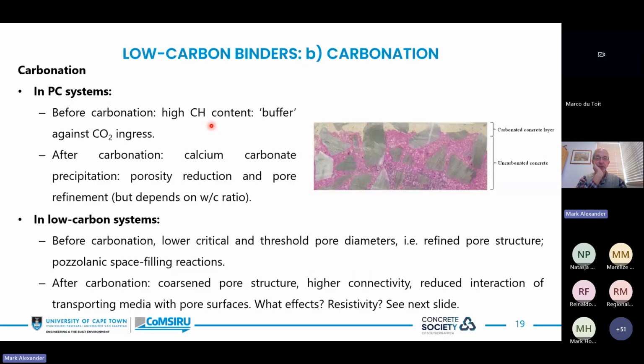Now, talking about carbonation, that's the other issue that frequently causes reinforcement corrosion. Here in PC systems, plain cement systems, before carbonation, we have that high alkalinity residual, which is a buffer against CO2 ingress. After carbonation, calcium carbonate precipitates in the pore space, porosity reduction and pore refinement may occur, depending on the water-cement ratio. So in fact, carbonation here is not a threat. It can in many ways be an advantage. It improves the concrete. It turns a thermodynamically unstable material, meaning portlandite, into a thermodynamically stable material, meaning calcium carbonate.